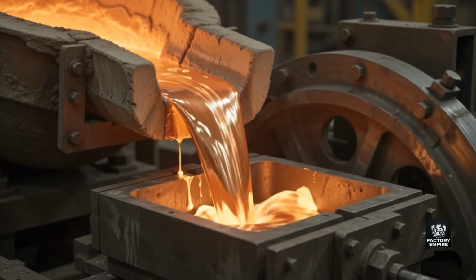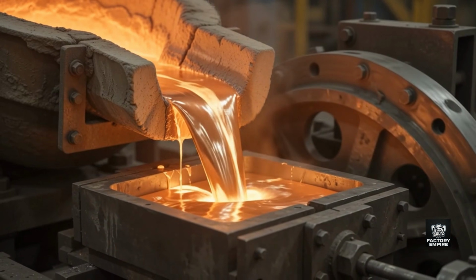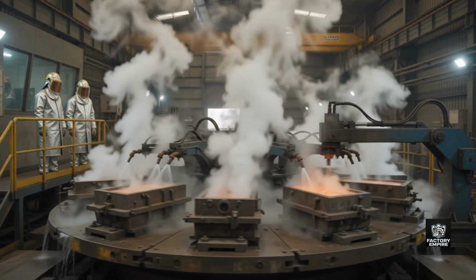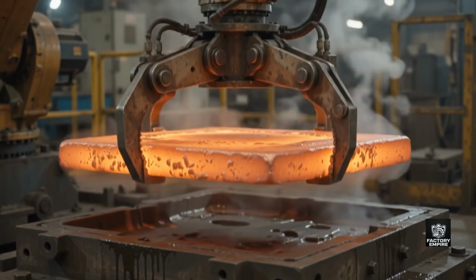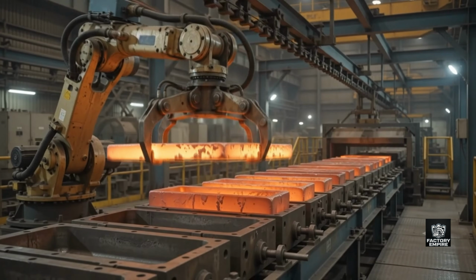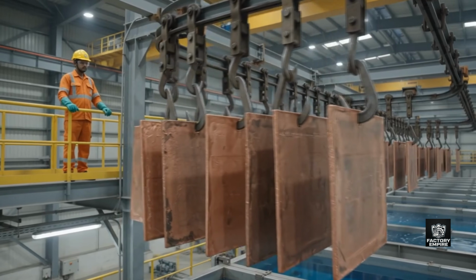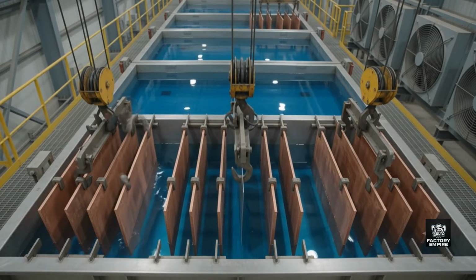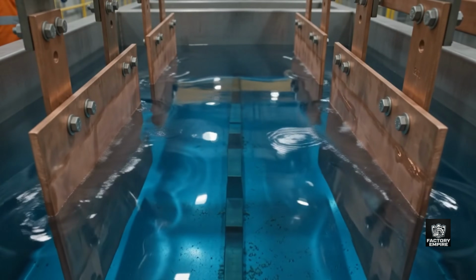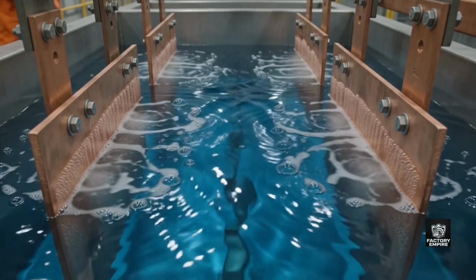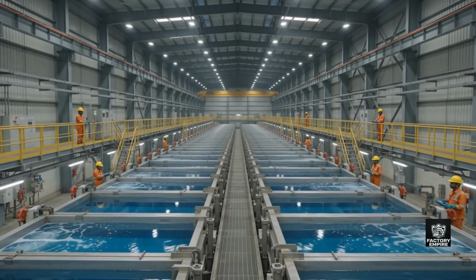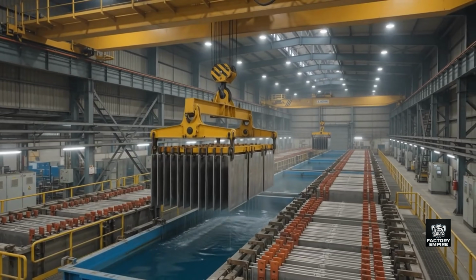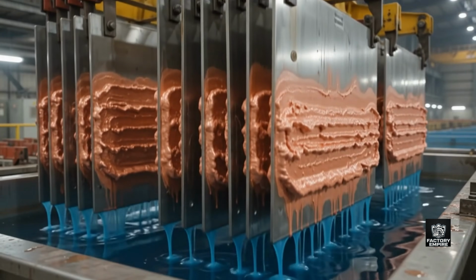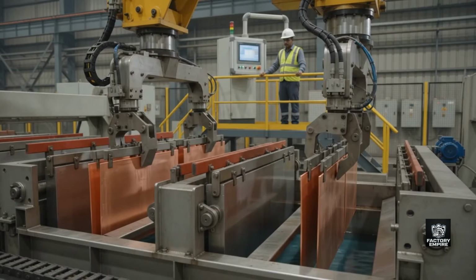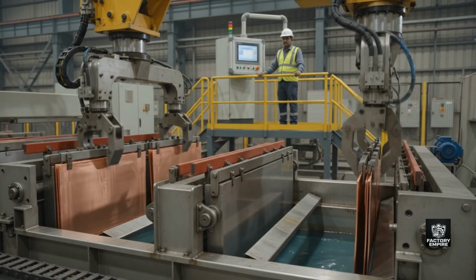The refined molten copper is cast into large anode plates using an automated casting wheel. After rapid cooling and solidification, the anodes are transferred to the electrorefining. The copper anodes are suspended inside electrolyte tanks between stainless steel cathode plates. When direct current is applied, pure copper deposits, and after several days of electrorefining, thick layers of 99.999% pure copper have formed on the cathode plates.